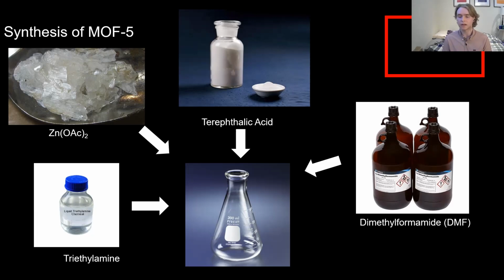But you can also add it at a very slow rate, perhaps over a day or 2 days, and you might be able to see something like larger single crystal growth, which can be useful for some things. But in my case, I was just looking for a uniform powder. So as long as throughout my synthesis I was able to maintain the same rate of addition, I was hoping to create a uniform powder there.